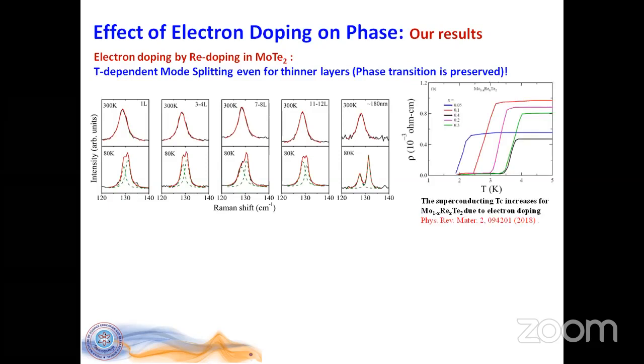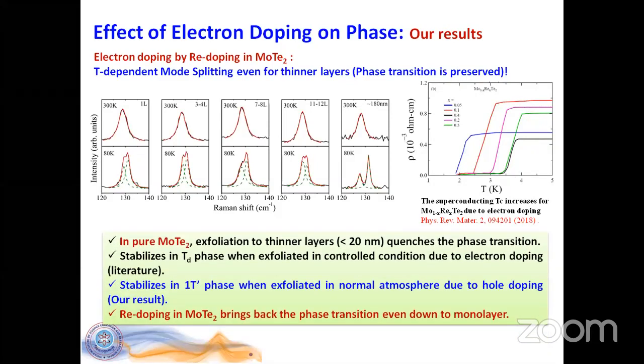Here is what Ravi's group also showed: with rhenium doping, there is an increase in the Tc. This particular MoTe2 is known to show superconductivity at very low temperature, and with rhenium doping, they showed an increase in the Tc. So that's where something interesting happens.